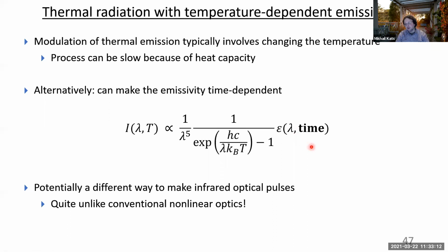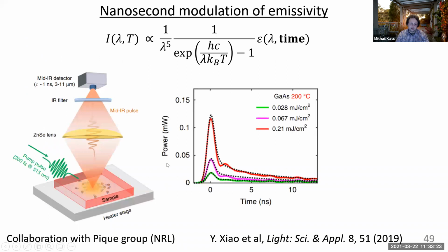In addition to looking at emissivity as a function of wavelength or as a function of temperature, we also took a look at emissivity as a function of time. The experiment that we did was an optical pumping experiment, in collaboration with Alberto Piquet's group at the Naval Research Lab. The idea was that we took a piece of undoped semiconductor, like a wafer of gallium arsenide here, or a wafer of silicon. We put it on a heat stage, here at 200 degrees Celsius, and we took this infrared detector over here. Normally, this sample doesn't emit very much infrared light because the emissivity of an undoped gallium arsenide wafer is almost zero.